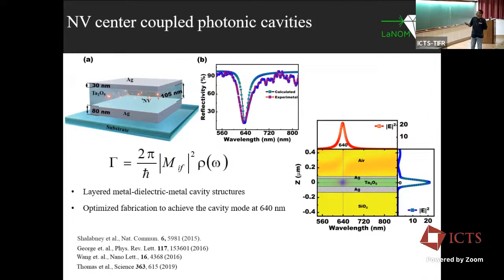So we simulated this and we got a cavity mode at around 640 nanometer. And when we measured in our lab with reflectivity spectra, the cavity mode is also at 640 nanometer. So this is what we designed. It looked very simple, but it took quite some time for us to get the kind of sample we wanted. Even though this cavity looks simple, in the literature it has been used for experiments like the strong coupling regime and cavity catalysis, published in PRL and another journal.